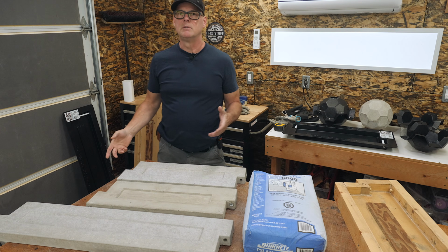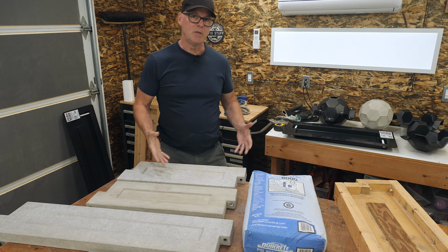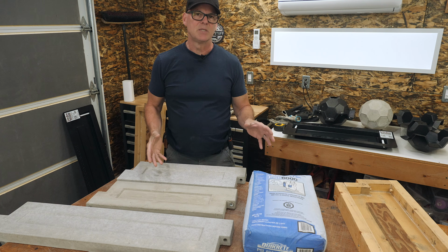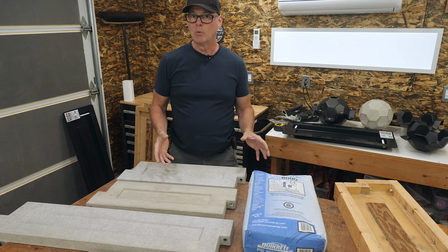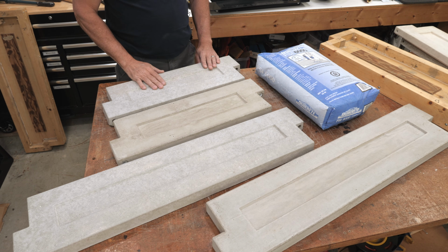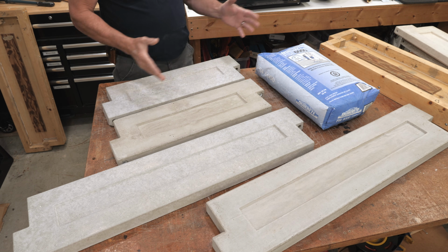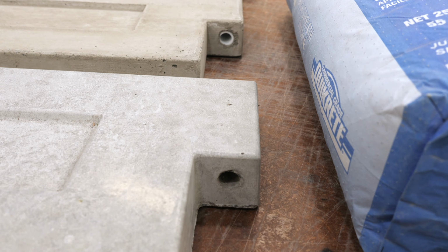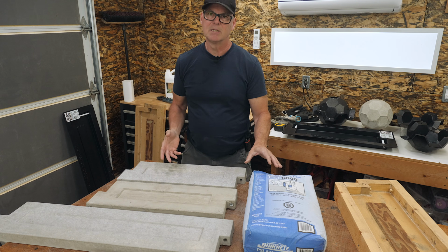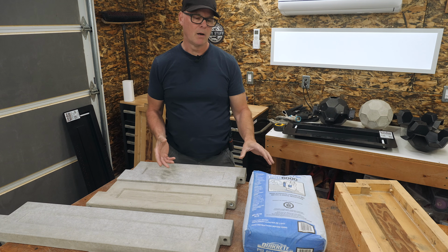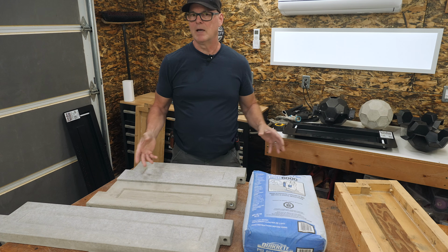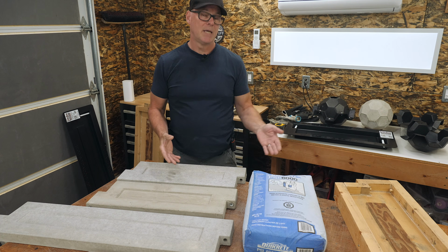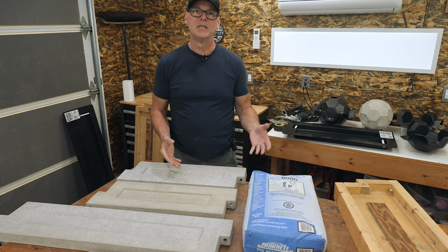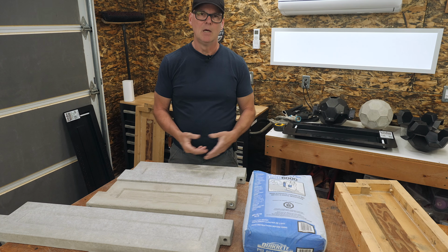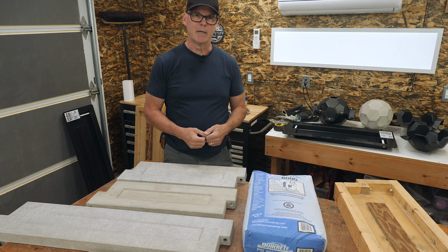For both my original wooden DIY molds and the ABS plastic molds, the 6000 psi ready-mix concrete worked well. The panels have a smooth surface without any visible voids, and around the pipes and holes everything looks sound. This 6000 psi mix may not be available everywhere. In some places you may find a 5000 psi blend. I've not tested the 5000 psi blend, but I suspect you would get similar results. Drop me a comment below if you've tried that mix.